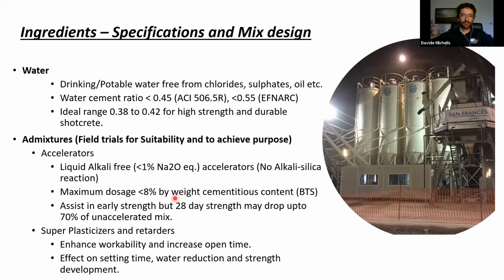Then accelerators. We have to add the accelerator right at the nozzle of the spraying equipment, in order to accelerate a few seconds before the shotcrete hits the surface of the substrate. Adding the accelerator at the nozzle causes a drop of the final strength compared to an unaccelerated mix, and this can be up to 70-75% of the unaccelerated mix. But consider that with an alkali-rich accelerator, the drop is not only 20-25%, but we can even reach a 50% drop. So it's very important to select the right amount of the right accelerator.